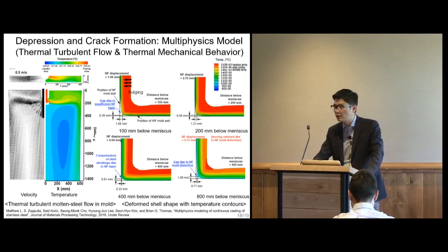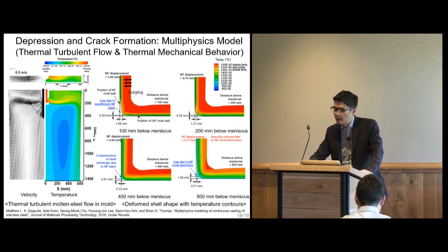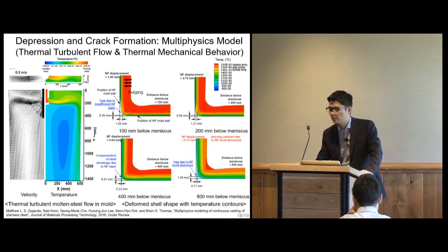Finally, we used the calculated superheat flux profile at the shell front as input data for the modeling of thermomechanical behavior of the solidifying steel shell. The thermomechanical model considers the phase transformation during the steel continuous casting. And from this model simulation, we can quantify the very important mechanism of the depression and the crack formation on the steel slab surfaces.